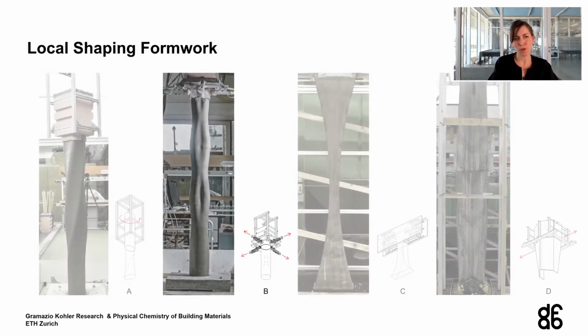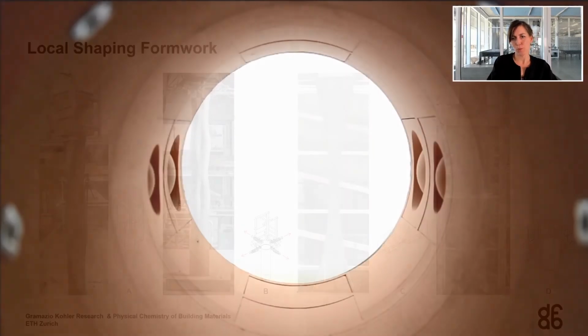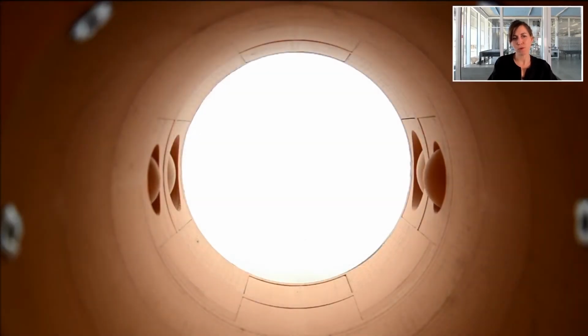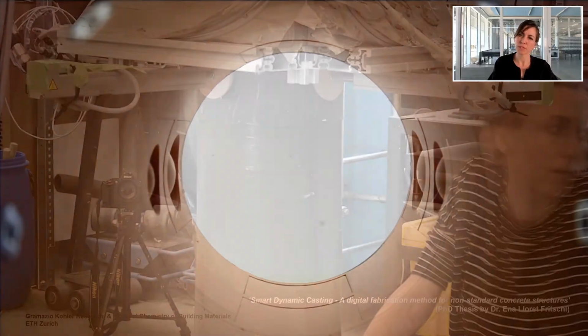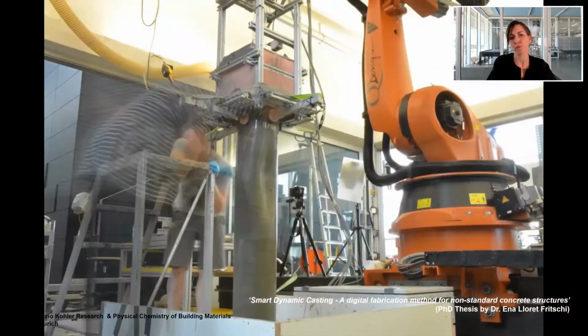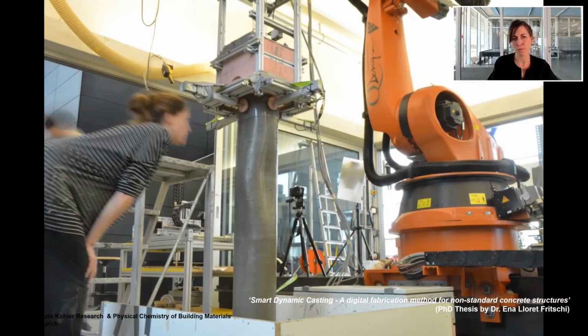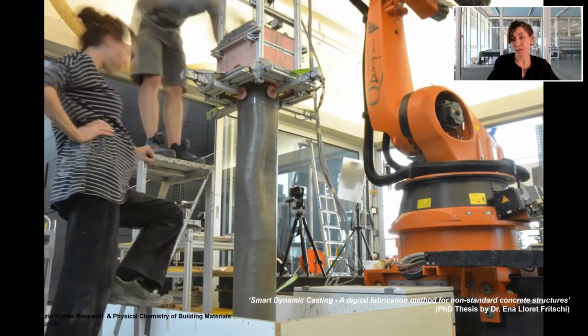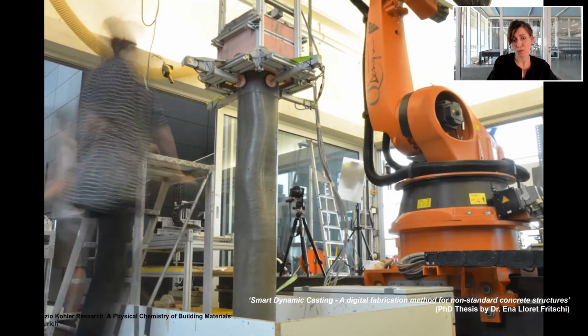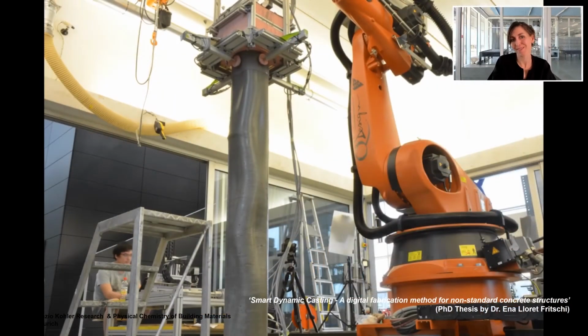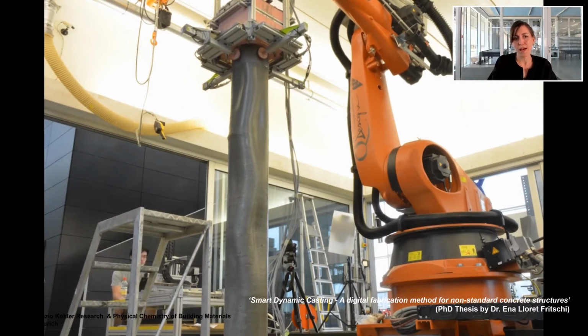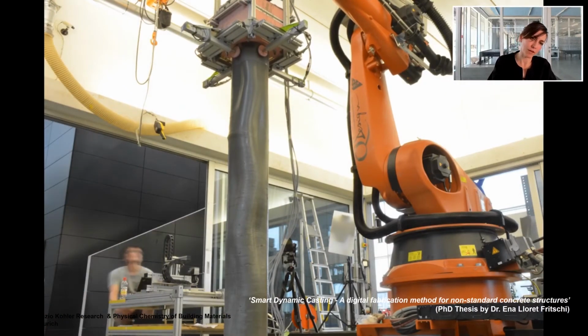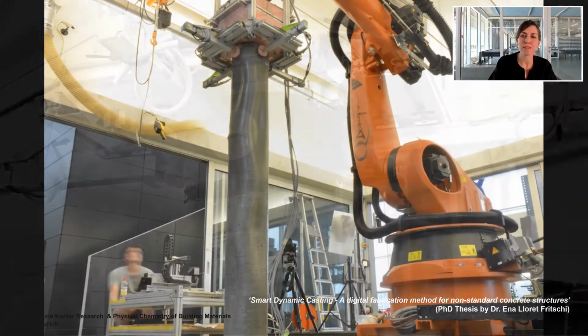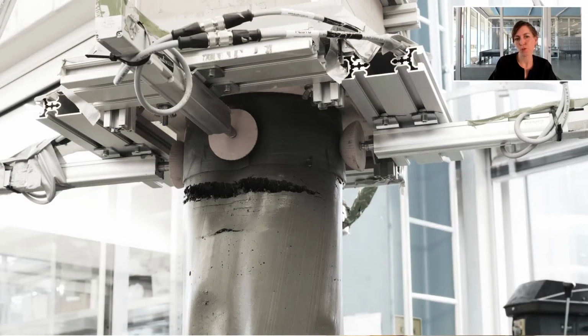So we started with what we call the local shaping formwork, where we had a 40 centimeter tall formwork in which we placed actuators inside. After some tests, we decided to place the actuators at the very bottom of the formwork to indent the column as we went upwards. To make this a success, we had to make the column hollow due to the fact that we are using a self-compacting concrete that is actually incompressible. However, despite being able to produce a couple of these tall columns, there was a very limited design space and a lot of issues in terms of friction and slip-stick effect inside of the formwork.